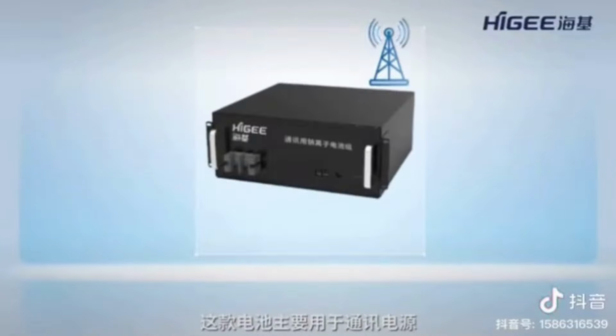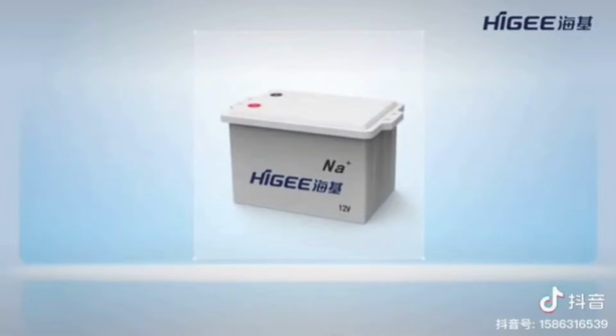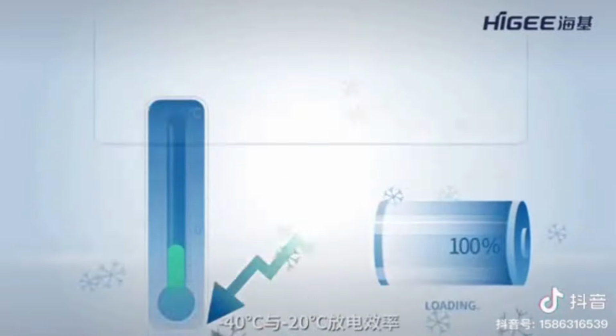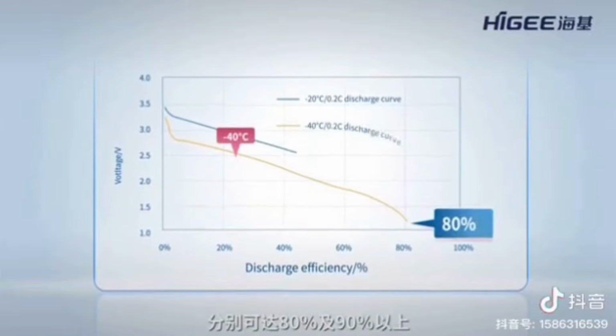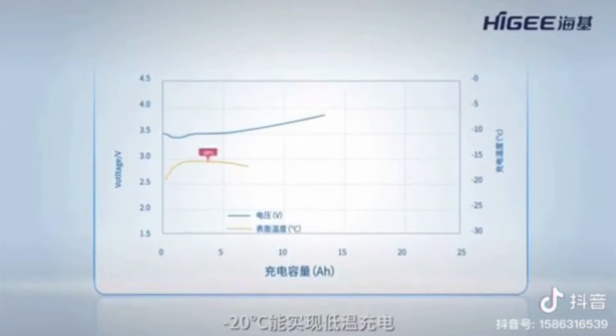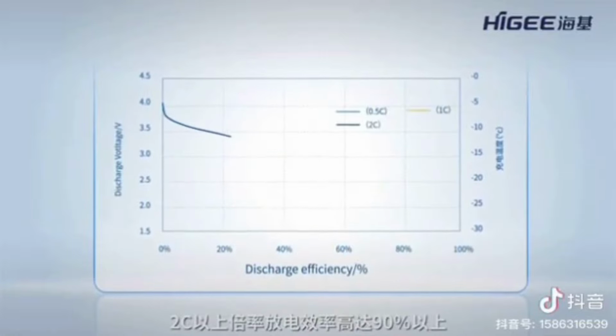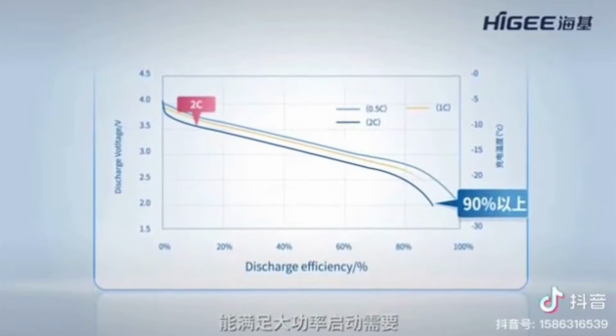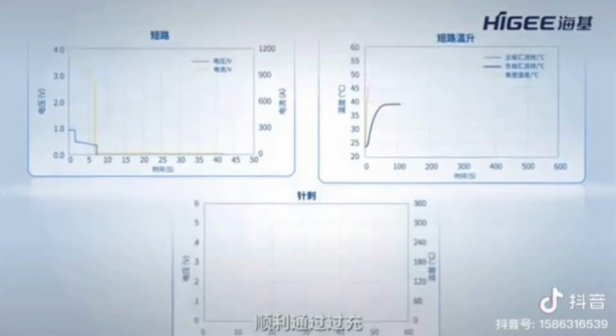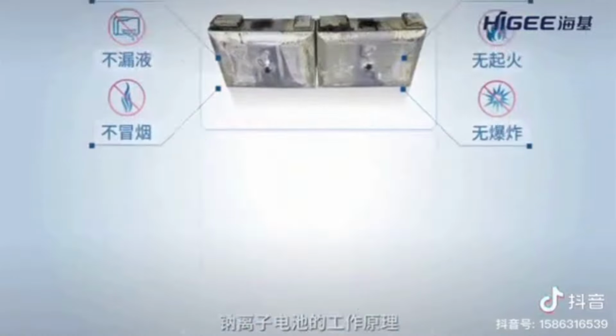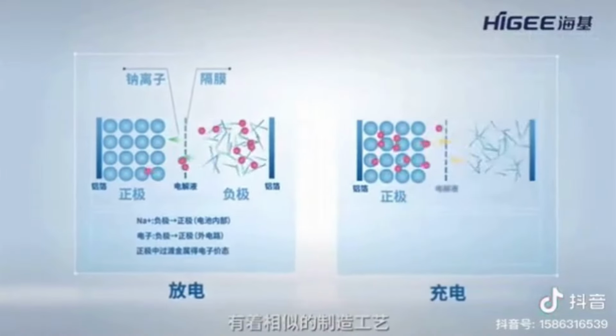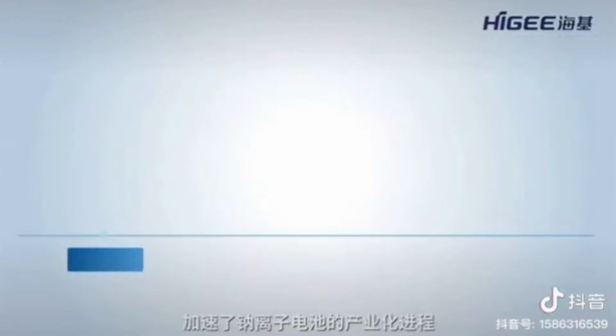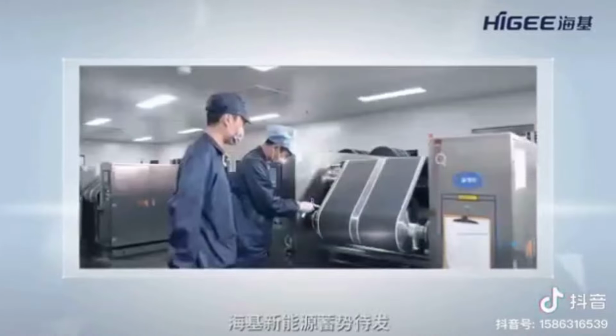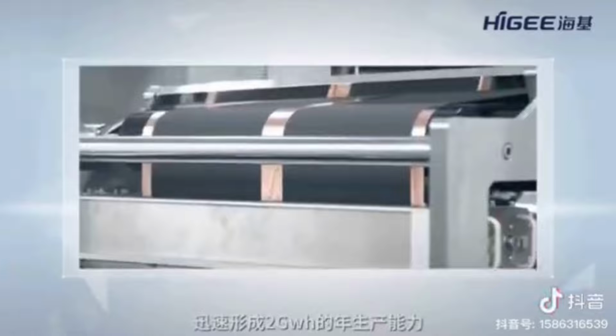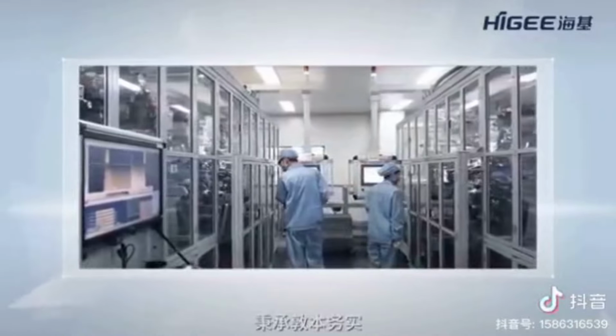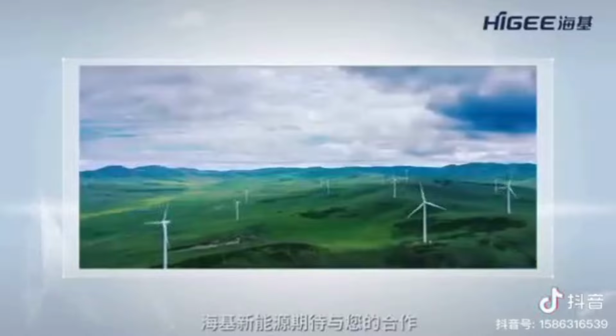The cells can operate between minus 20 to minus 40 degrees C and can demonstrate fast charge capabilities of up to 2 C with up to 90% efficiency. 0.5 C, that's 2 hours. Sodium-ion battery cells have successfully passed several puncture and fire tests that prove their safety in comparison to lithium-ion batteries. Higee currently has a 2 gigawatt-hour cell production plan for LFP and sodium-ion batteries in China, and it has plans to increase capability to 10 gigawatt-hours in a few years' time. So you can see some LFP battery manufacturers are switching to sodium-ion batteries gradually.